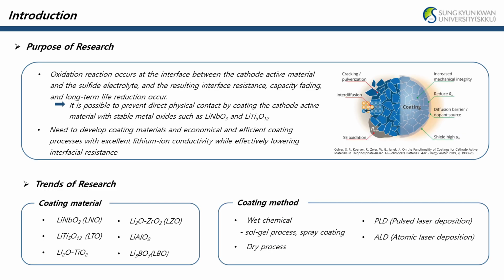The oxidation reaction at the interface between the cathode active material and the sulfide electrolyte occurring in the sulfide solid-state batteries causes interfacial resistance, capacity fading, and a decrease in long-term life. This can be solved by coating a cathode active material with a stable metal oxide such as lithium niobate to prevent direct physical contact. Therefore, it is necessary to develop coating materials and economical and efficient coating processes with excellent lithium-ion conductivity while effectively reducing interface resistance.